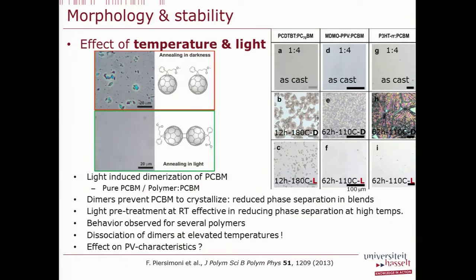The two previous images were obtained when we submitted these films to elevated temperature but in dark. What happens now when you put light on it? So again, this is what you have when you do the annealing in dark. When you do now the same annealing at the same temperature but you apply light, you see that no phase separation is occurring. So for us that was quite a surprise.